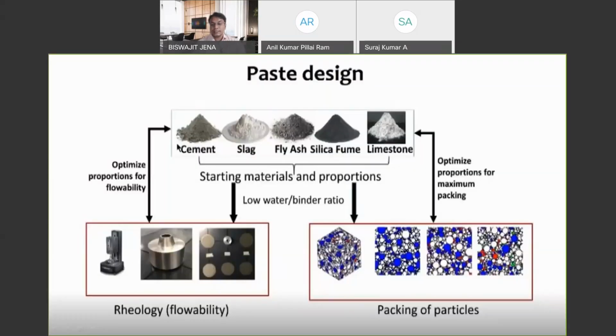So the first strategy is to design the paste, and this is the most crucial strategy. It is not because nobody knows how to design the paste, but because you have so many different combinations of materials that you can choose for paste. So the first idea should be what is locally available. Everybody has cement. Slag is generally available. Fly ash is generally available. Silica fume and metakaolin are not very hard to get, and most of the time people are using ground quartz, because they take ground quartz and grind it really fine to improve the reactivity.